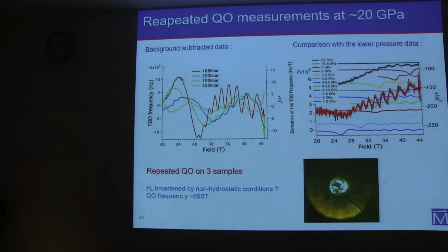So here, what's really important is that we have the critical field that's of the order of 29 Tesla. And if you remember, at 70 kilobar, the critical field was of the order of 44 Tesla. So for me, this is the main argument that we have pushed the sample to the other side of the dome, the other side of the superconducting dome. So we are on the other side of the superconducting dome.